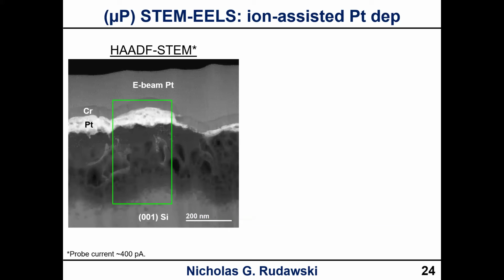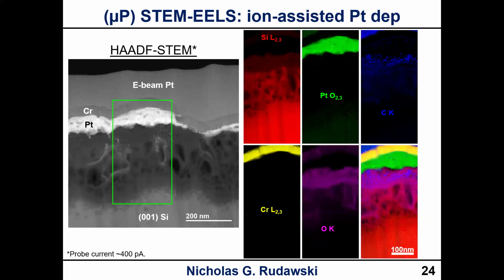prep. So if we use this area to map, we can map five elements. We'll map the silicon, the platinum, the carbon, the chromium, and the oxygen. And we can render all this together, and we're still seeing detail here that's deep into the nanoscale. You can see, particularly with the silicon and the carbon, resolving features that are really small, down around a nanometer or 2 nanometers here. And that's exactly what we would expect, just like we were doing with the EDS.